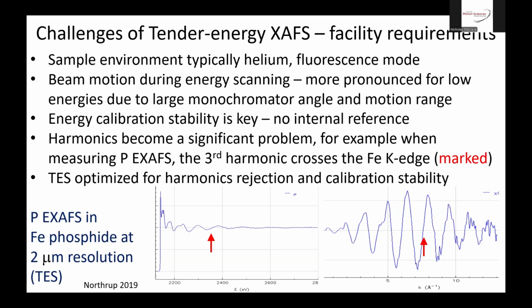Beam motion during energy scanning is a problem for microbeam work, and it's more pronounced at lower energies because the monochromators have to travel longer distances and at steeper angles to reach those energies and to make those energy scans. So it's harder to achieve, but we've gotten that fixed in some locations. Energy calibration is also key because you don't have the luxury you have at hard X-rays with transmission geometry, where you've got an energy calibration reference in line with your sample. Obviously, you can't do that at lower energies. So you have to make sure that the energy calibration is very stable for the beamline that you're using.